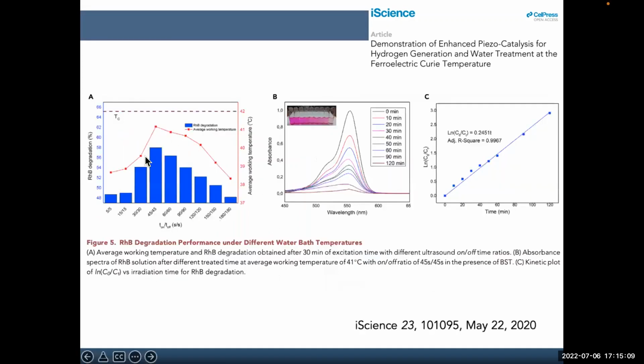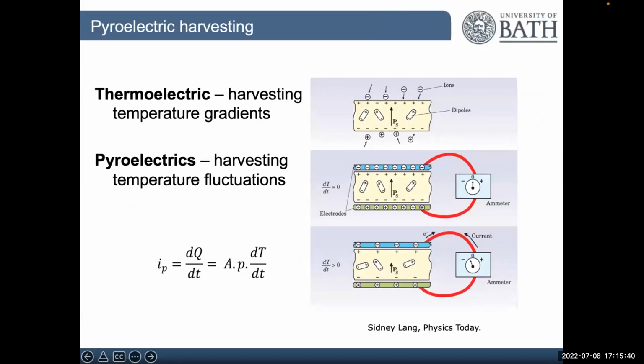And the same happened also for dye degradation. So again, when we operated our system closer to the Curie temperature, when the material is more active, when the change in polarization under a stress is easier, and so all these d coefficients increase more greatly, we were getting better degradation of contaminants such as rhodamine B. Again, it also fell as we went above the Curie temperature.